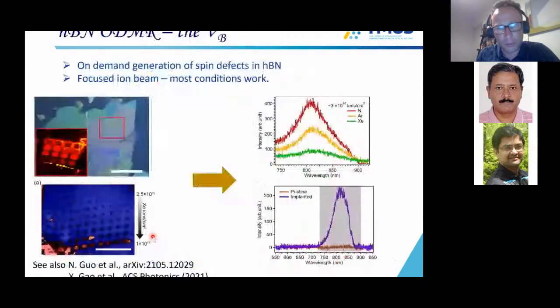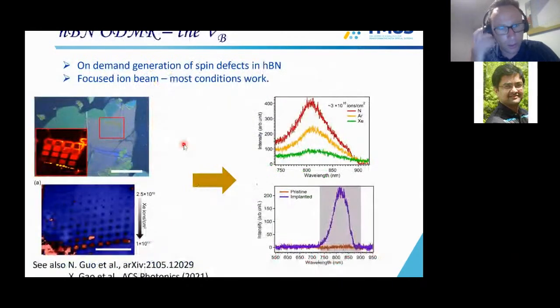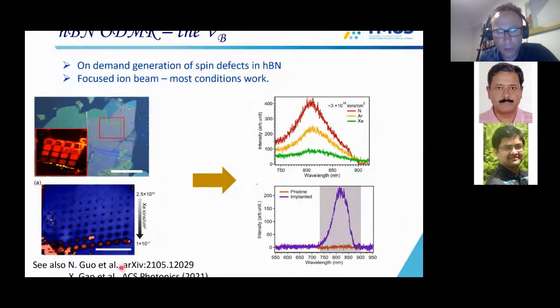Now, what's cool about the system, again, is the fact that you can make it in a monolayer or in a few layers of hBN. And because it's just a missing boron, you can easily make them on demand. And so we made arrays here. Every spot here is an array. There were also other people already working on that as well. And you can make it with a nitrogen beam or argon or xenon.